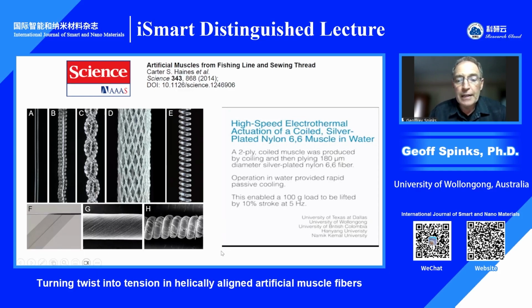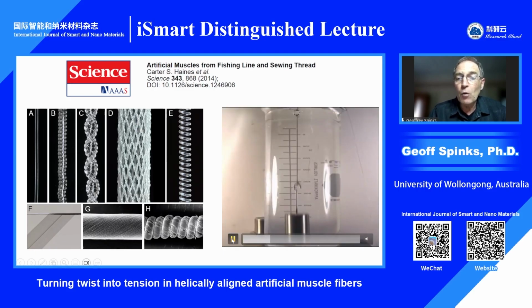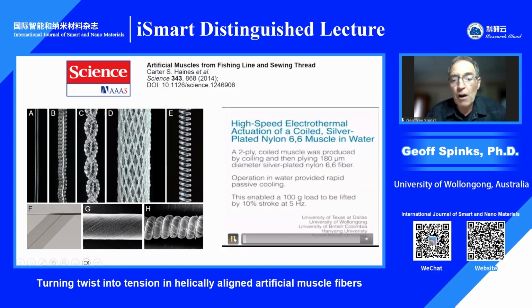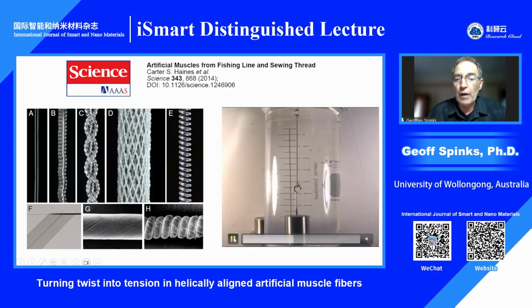So this is a Joule heated thin fibre, which has been made into a coil, and it's sitting in a water bath to cool it quickly. You might be able to just see that there's an electrical wire connecting the ends of the sample. It's actuating at 5 Hertz with a 100-gram load in water. So this is kind of typical performance.